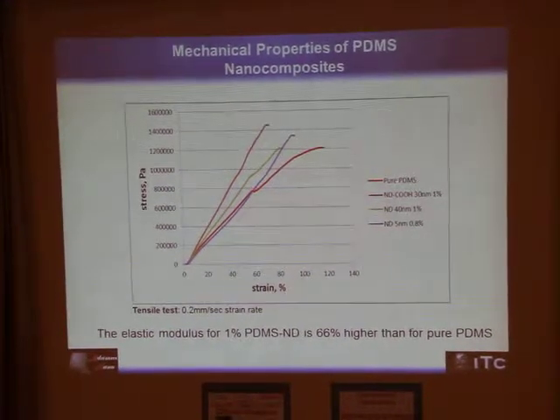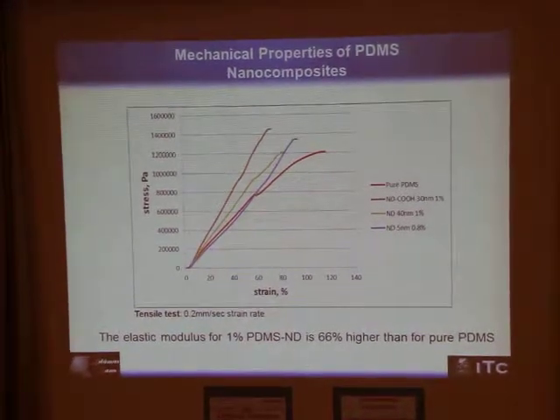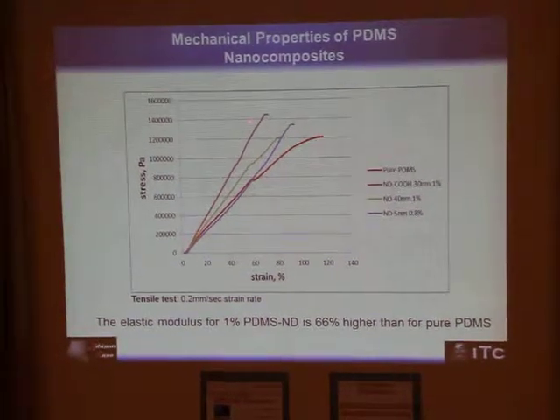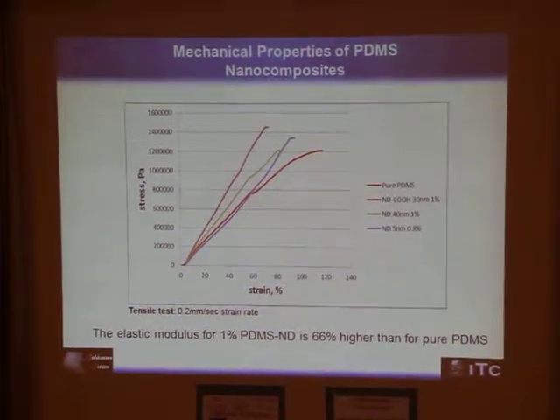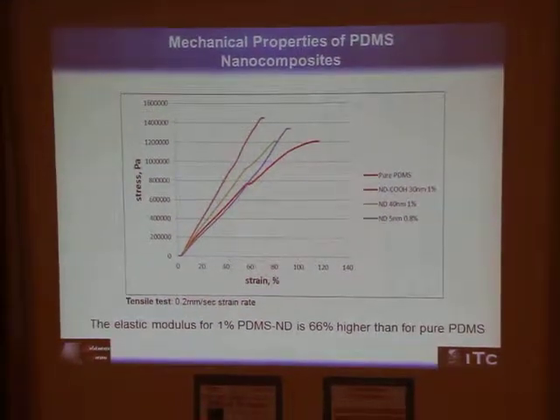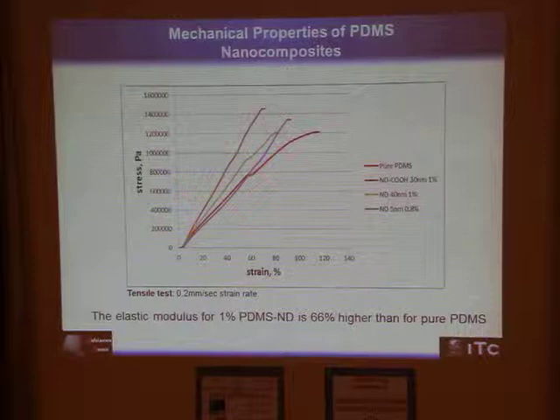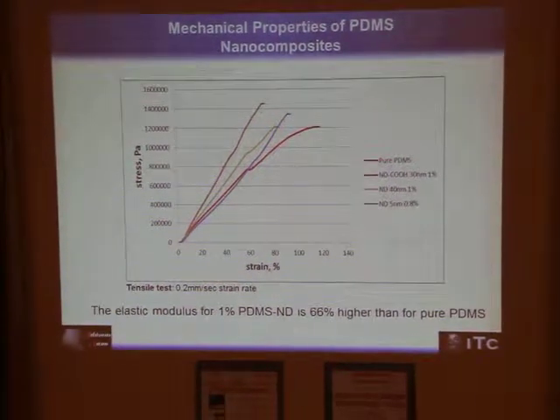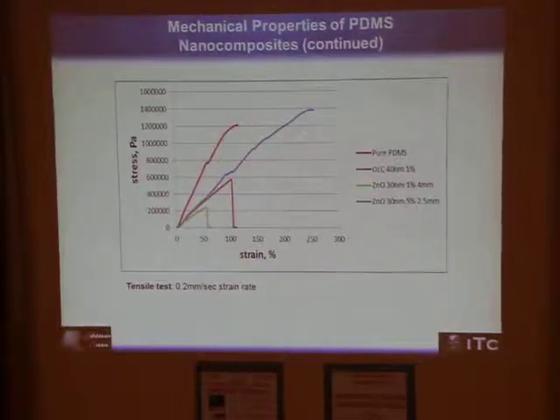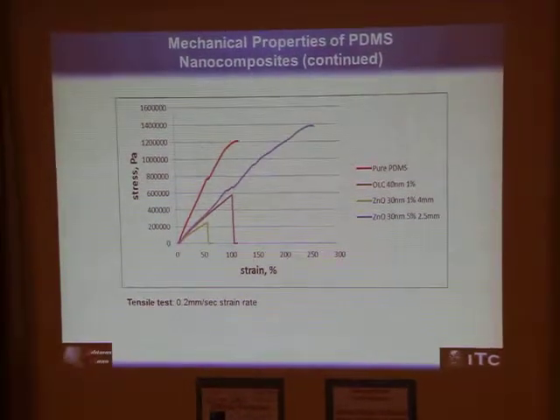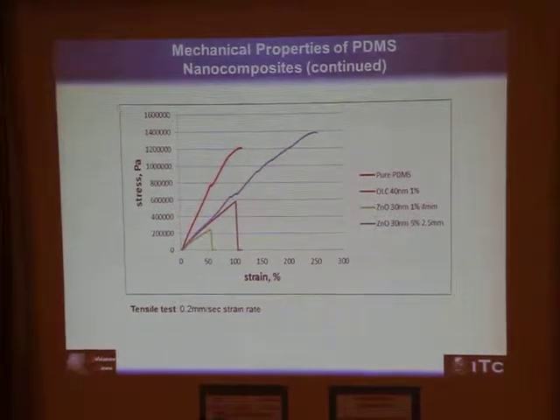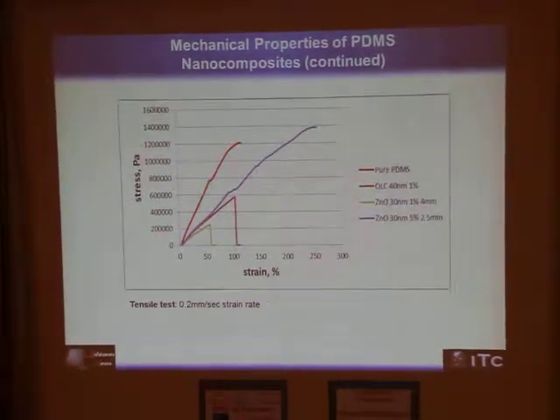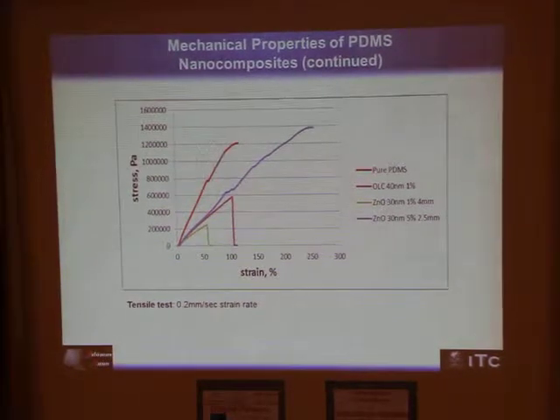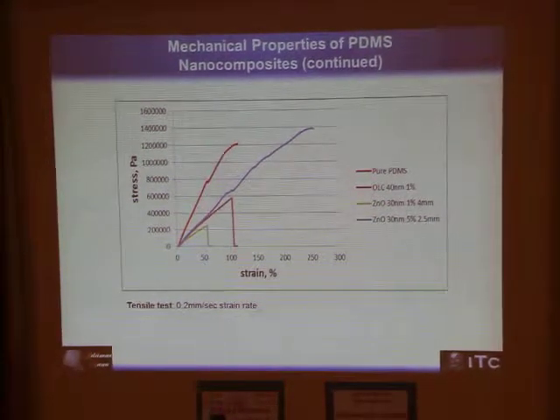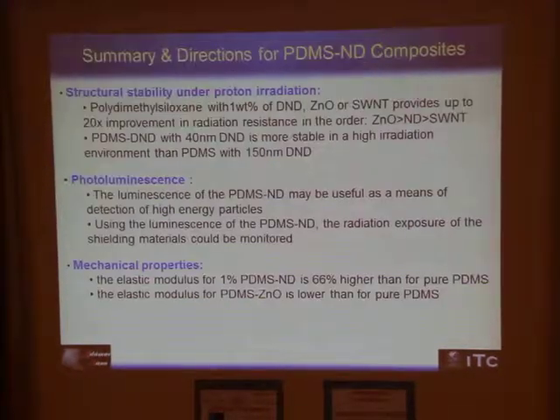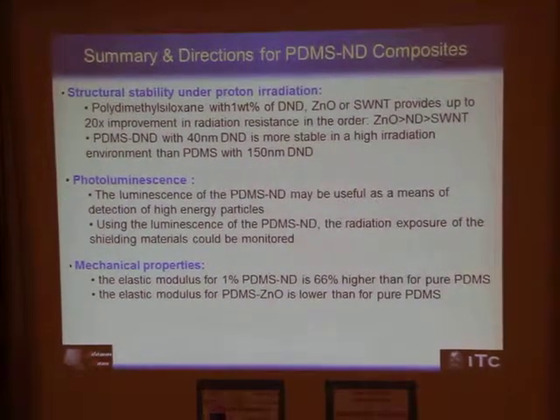And the final slides are on the mechanical properties. Nanodiamond significantly improved elastic properties of PDMS, especially carboxylated nanodiamond and seleniated nanodiamond. Data is not shown for seleniated. At the same time, zinc oxide nanocomposites prepared at the same condition showed elastic modulus lower than that for pure PDMS. So in our case, zinc oxide didn't provide enhancement of mechanical properties.